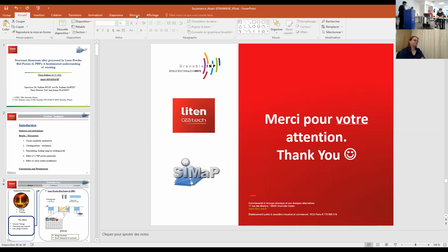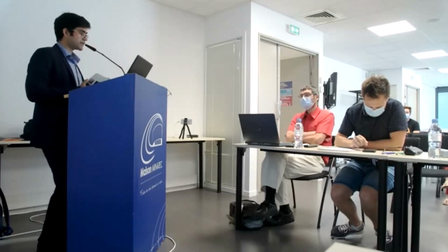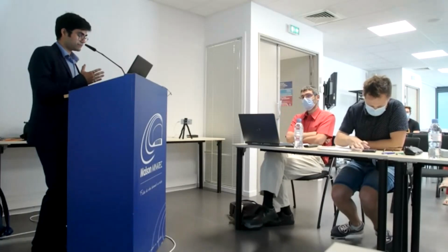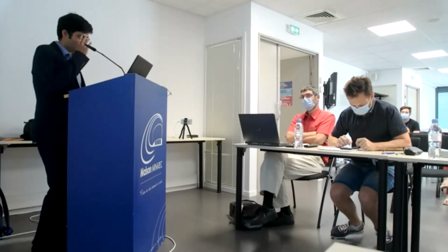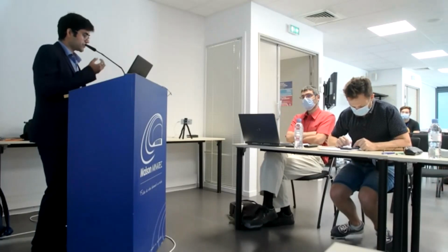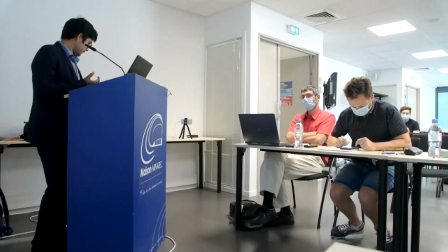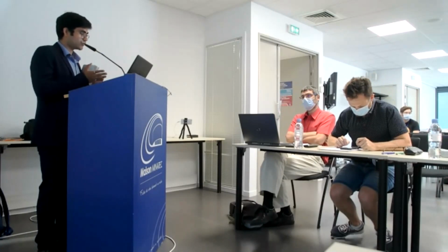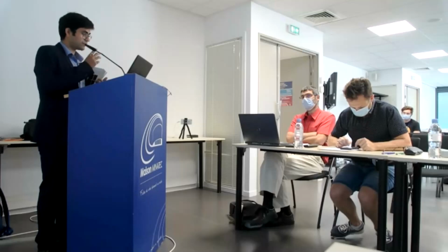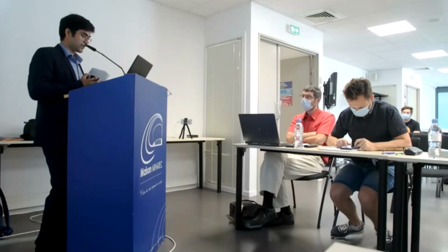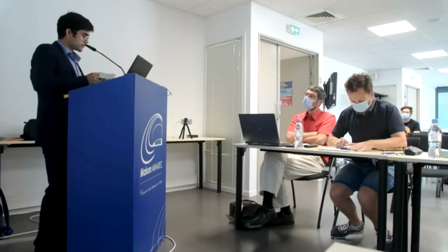Yeah, in fact, the goal was to identify whether we have a real effect of the particular grain boundary we are looking at, for example, whether there are particular elements which are segregating along the grain boundaries. To identify this, we selected two grain boundaries. One is cracking and one is not cracking. Both grain boundaries were high angle in nature, but we observed a slight difference in the precipitation of the different elements along the grain boundaries. But in order to conclude that this particular cracked grain boundary, which is high angle in nature, is giving some particular continuous precipitation of elements along the grain boundaries compared to the non-cracking grain boundary,